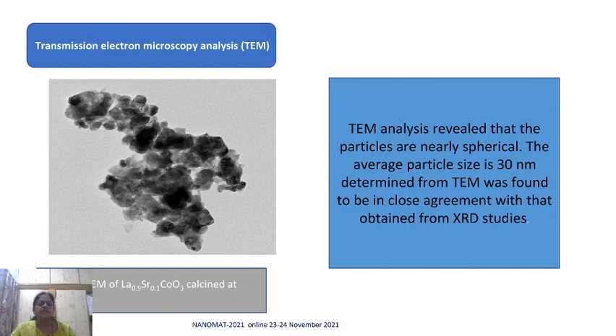The second characterization was the transmission electron microscopic analysis. As you see in the figure, the TEM image of LaSrCoO3 calcined at 550 degrees Celsius. The TEM image revealed that the particles are spherical in nature with an average particle size of 30 nanometer, which is in close agreement with the result obtained from the XRD.